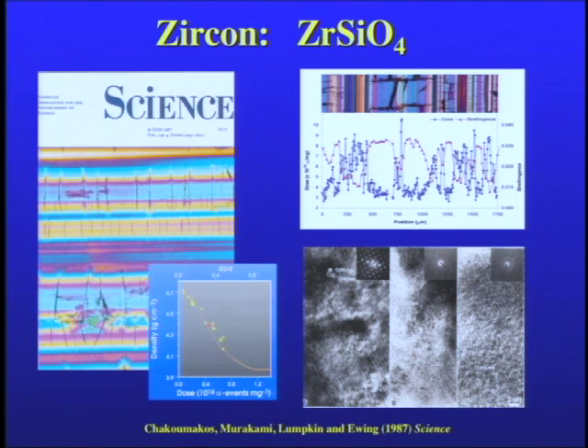I knew the uranium-thorium content, I knew the age of the crystal, I could calculate the dose and measure changes in properties, and what we did was, it was the first application of transmission electron microscopy to this. Microscopes are much better now, but we could see the amorphous domains, the intermediately amorphous domains, and the early damage in the material.